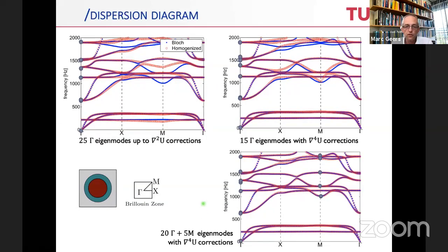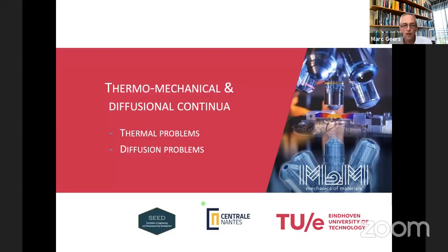For every mode, you have a macroscopic displacement, which is the magnitude of that particular mode. Don't forget, which means that in the physical problem, you say what the displacement is, but here all of a sudden, you have perhaps 25 degrees of freedom in that point, which makes that your boundary conditions are not unique. And that is quite a challenge, to seek the right boundary conditions. So also not a completely solved problem, so there's still work to do there. Okay, it brings me to the translation now to the thermomechanics and the diffusion continua.